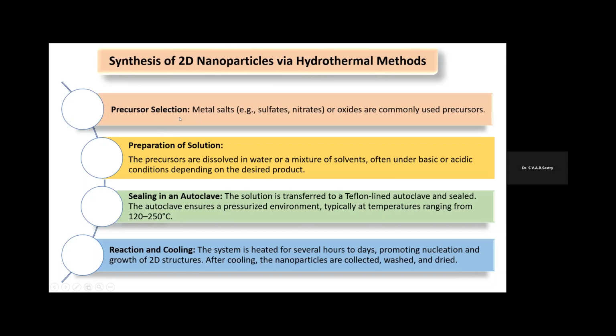So to make the nanoparticles, we have these things to be done. First is precursor selection. We can select metal salts, either sulfates or nitrates or oxides, used as precursors. Then we have to prepare a solution. The precursors are dissolved in water or a mixture of solvents, often under basic or acidic conditions, depending on the desired product. Then we have to seal it in an autoclave. The solution is then transferred to a Teflon-lined autoclave and then sealed. The autoclave ensures a pressurized environment, and typically the temperature is between 120 degrees Celsius to 250 degrees Celsius in the autoclave.